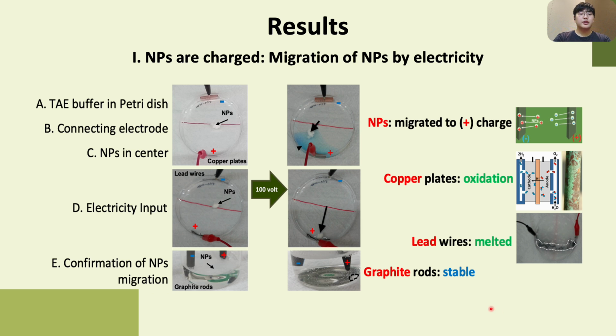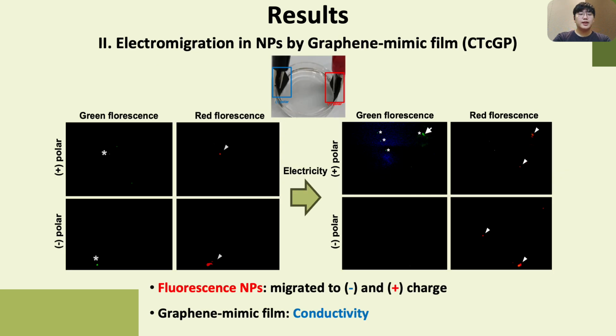As a result of checking the electrical mobility of the nanoplastics by using copper plates, lead wires, or graphite rods, I confirmed nanoplastics migrating toward the positive electrode. It is noteworthy that the copper plates or lead wires were severely destroyed, whereas graphite rods remained stable. It means that graphite can be used for optimal electrodes. Second, I confirmed whether the graphene mimicking film has electrical conductivity while the fluorescent nanoplastics are charged. The results showed that the fluorescent nanoplastics were detected on the surface of the graphene mimicking film.